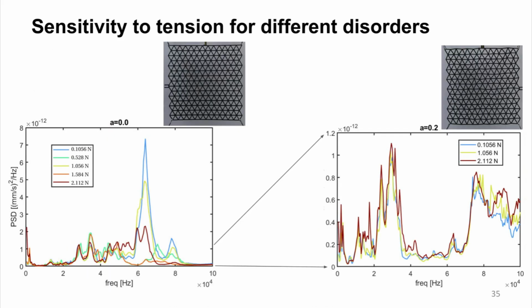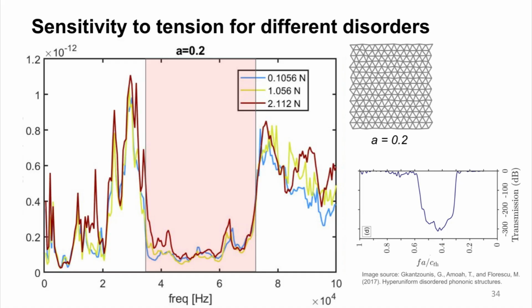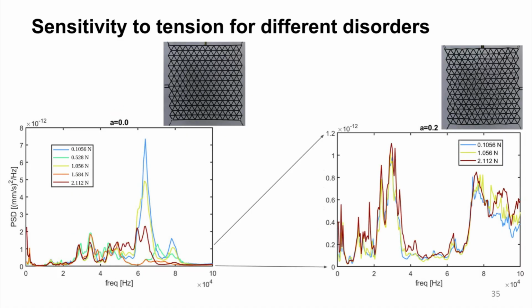This is what the literature had; the computational studies have already predicted. To compare the scale at which this is happening as compared to the ordered lattice, as we can see here, the peaks in the ordered lattice are of the order of magnitude of 7 PSD. However, the peak is completely suppressed once we add a small disorder of 0.2, and the band gap region exists below 1.2 PSD on these curves.